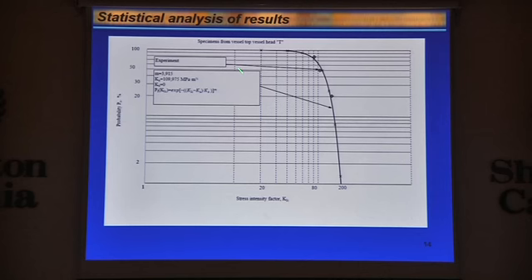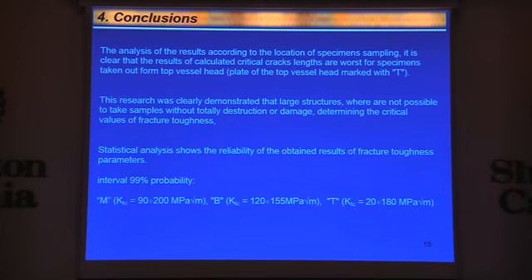So here we can see that in the case of the top, our interval for 3 specimens is quite wide. It is not so narrow, which means that in this case it is necessary to repeat more tests to get more reliable results. So the conclusion is that analysis of results according to location gives different values. It is also connected with the different microstructures.